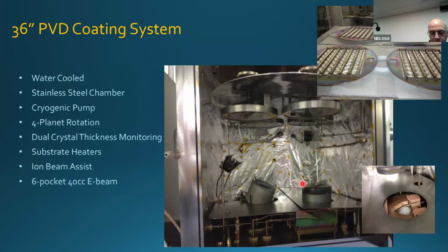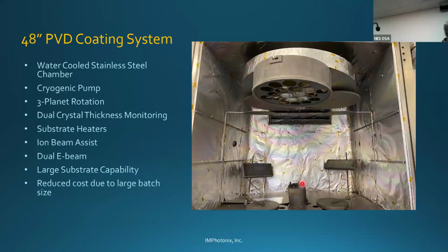With the larger chamber, we actually have two e-beam guns, where we can put in 4 materials on the one on the left, and then an e-beam gun on the right. It's actually a big circular crucible that we just fill with SiO2, one material, so that we can alternate between the two. The benefit of a system like this is that as soon as one layer is done, the other e-beam gun is ready to go, so there's very little lag time between each of the layers.